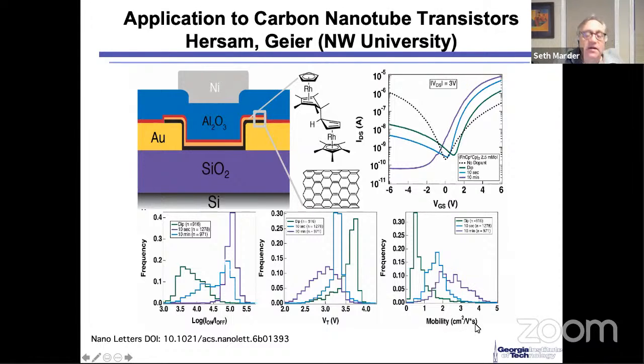So what we've done in this experiment is taken a p-channel material. We didn't go and invent a new material. We just exposed it to a very dilute solution of the dopant for 10 seconds. And now, boom, you have an N-channel material. I'll point out that we've done some work with other people where now they're seeing things that have mobilities on the order of, I think, 8 centimeters squared per volt second. And it doesn't change that much in air. I didn't include that data here.